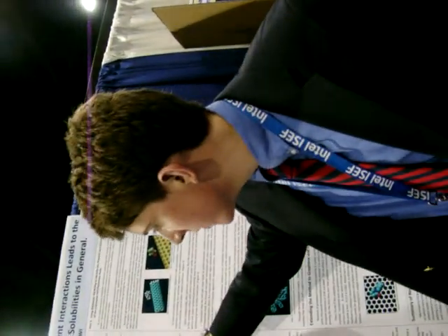And so I then plotted the calculated chi's, the Flory-Huggins parameter, versus the different solvents' surface tensions, and I was surprised to see what looked like a negative peak in chi centered around the data point for NMP. And so to try to clarify this peak, I searched for a long time for any similar solvent molecules with surface tensions around NMP's, but this was the big problem. I couldn't find any. And so I decided to mix solvents to get several more data points around this peak.